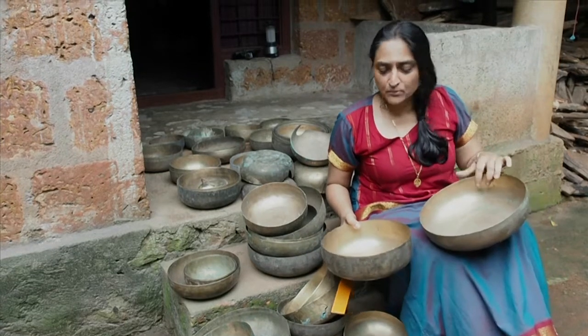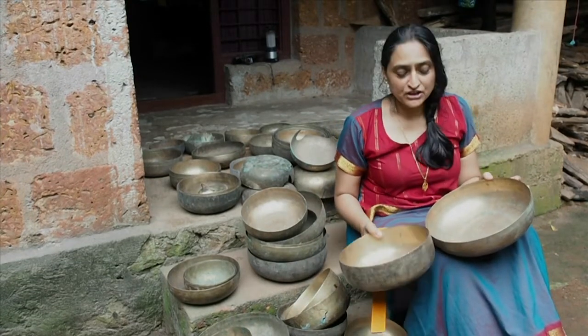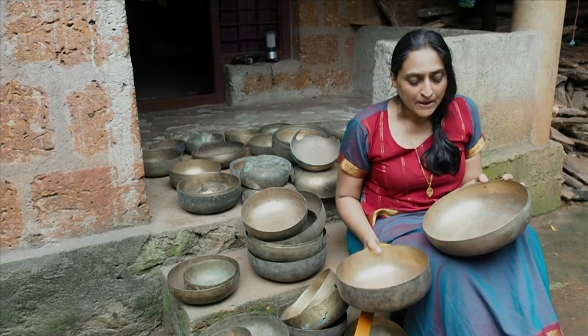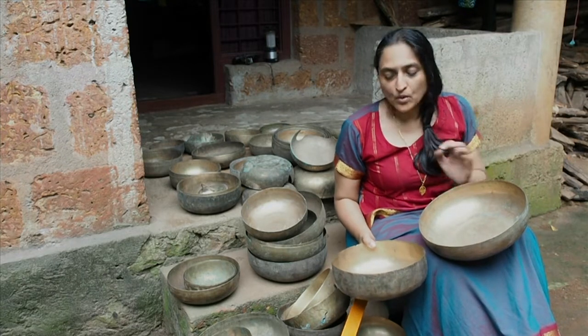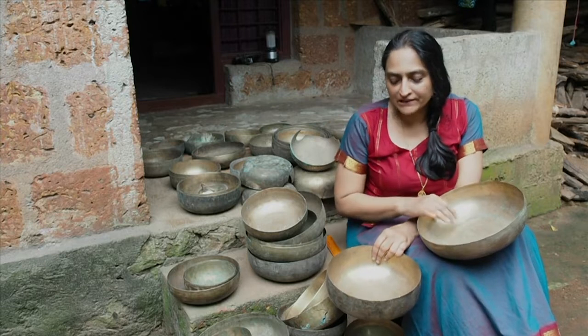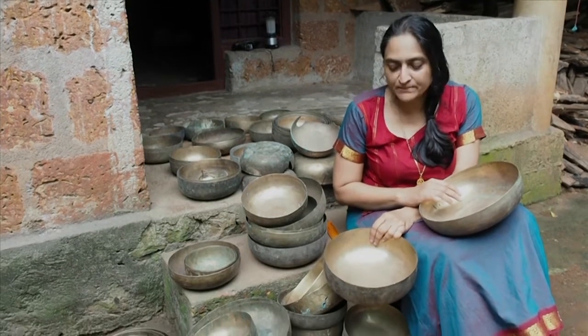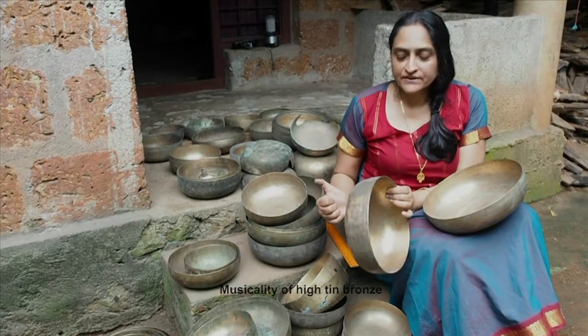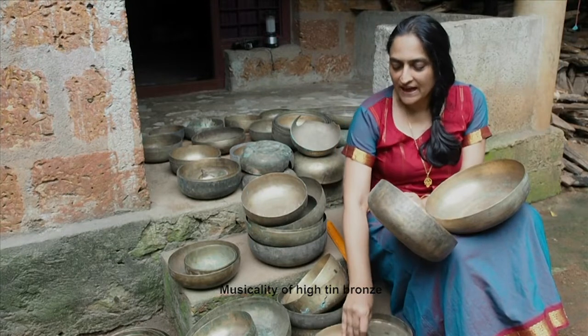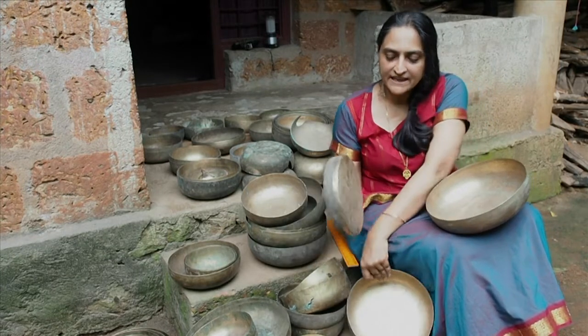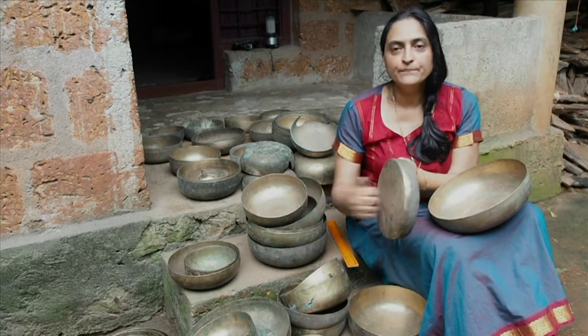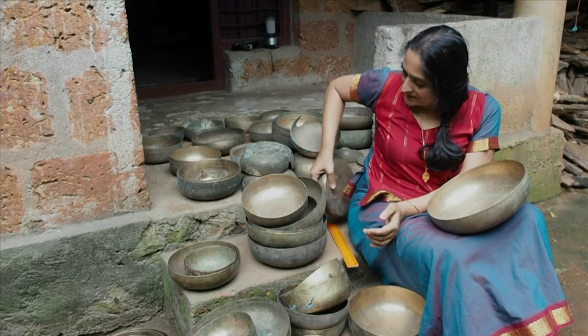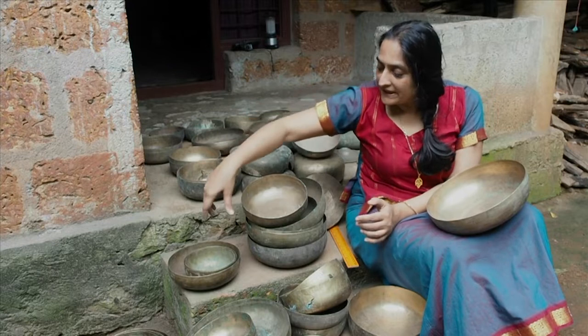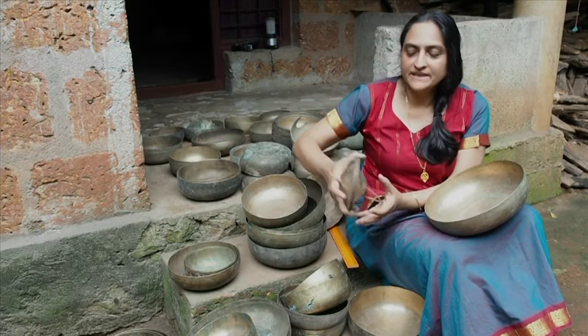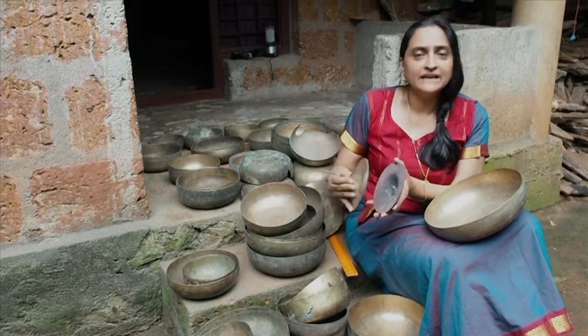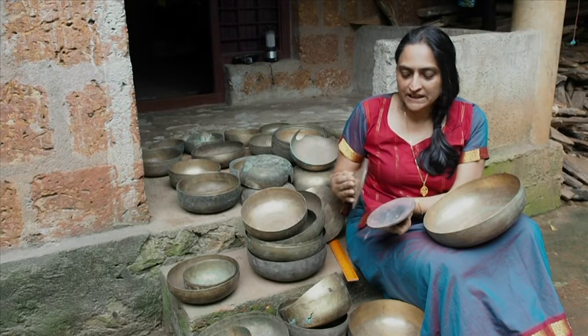It's also a very sad and poignant moment because these are not going to be entering a museum where they should be, the rightful place for all this rich heritage of Kerala. But these are all destined as scrap, because there has also been a parallel tradition of making cymbals of high-tin bronze of 23%, because this alloy is a very musical alloy, and the quenched martensitic bronze has very good musical properties, which were also recognized in antiquity in India and Southeast Asia. Gongs were made by a very similar process of making alloys of high-tin bronze of 23% tin, and then forging them and quenching them. And these cymbals have been made by exactly these processes.